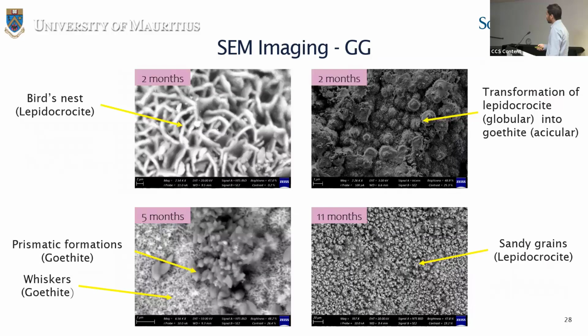At the extreme marine site, after 2 months of exposure, we could see transformation of lepidocrocite, which occurs as globular formations, into goethite, which occurs as acicular, that is needle-like, formations.